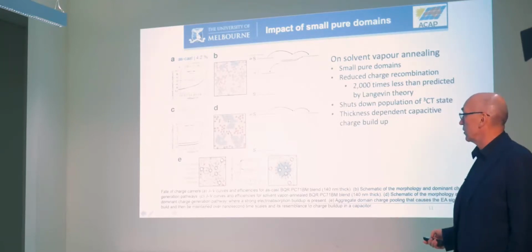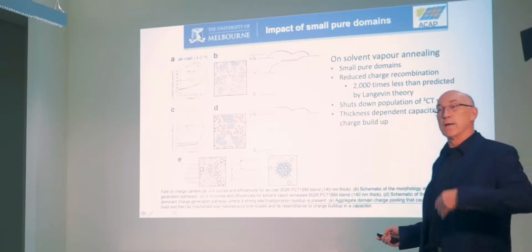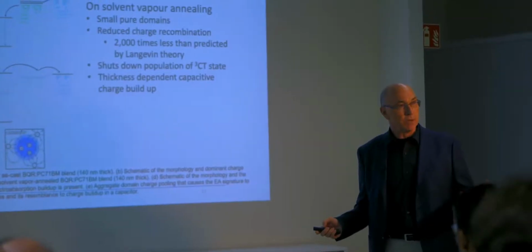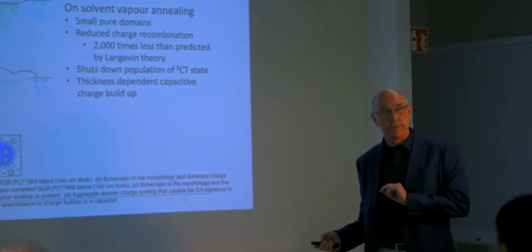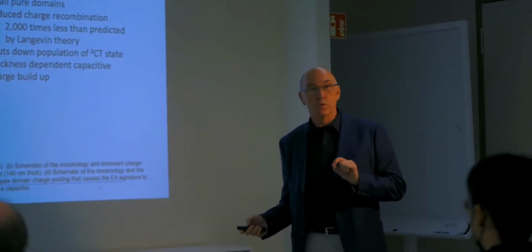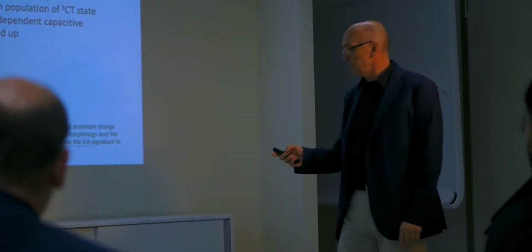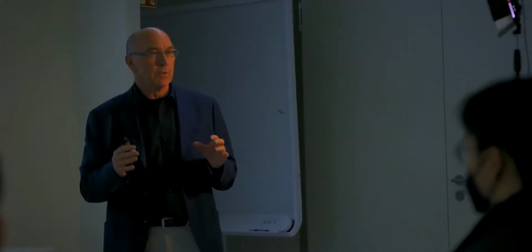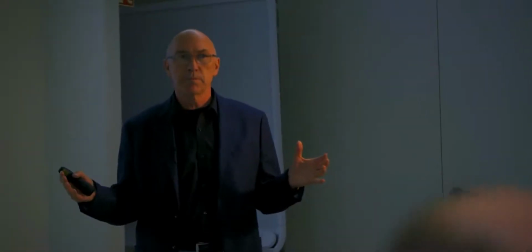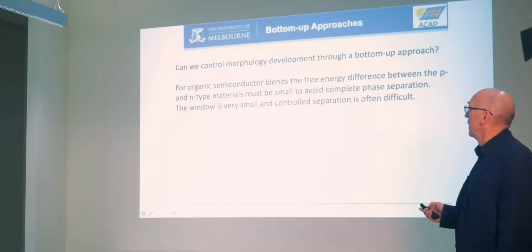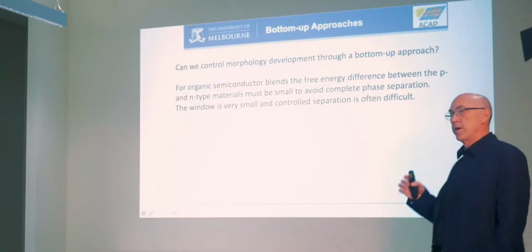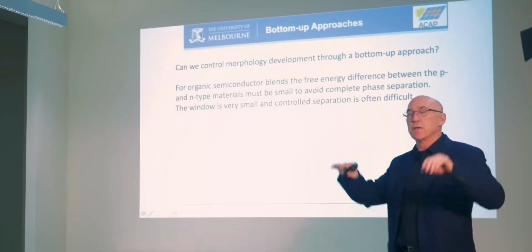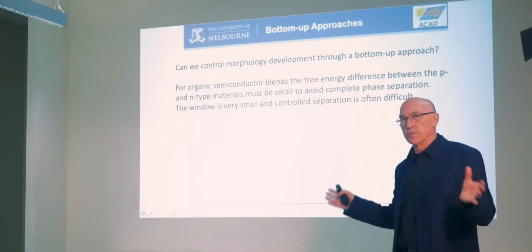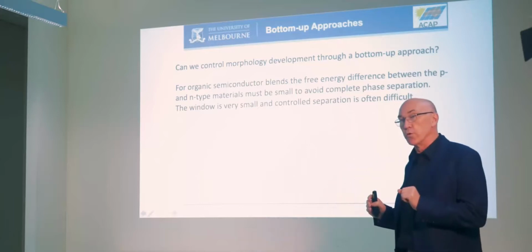A couple of the postdocs we had working on these materials to start off with, they've gone away, set up their own groups. They now have been modifying these, and they're the best materials with non-fullerene acceptors if it's all small molecule devices. They work really, really well. But we're not controlling our domains very well. So what we want to do is to see whether we can get rid of this whole process of having a kinetically trapped device. And so can we control morphology through the development of a bottom-up approach? Okay, control our chemistry to actually control the domain size, control the phase separation. And so that's what we want to do going forward.